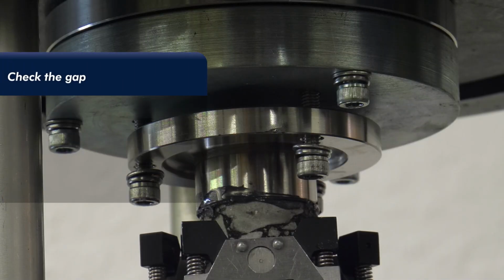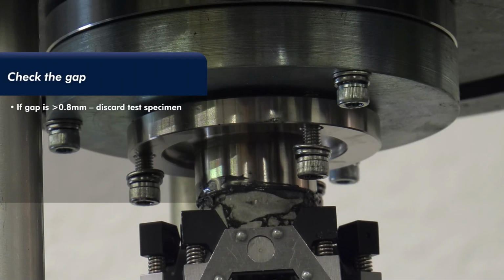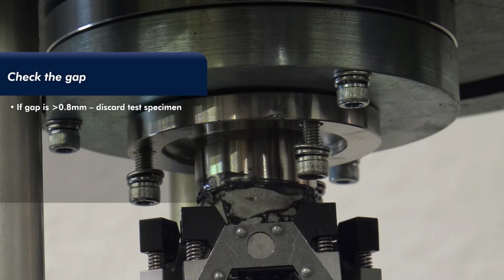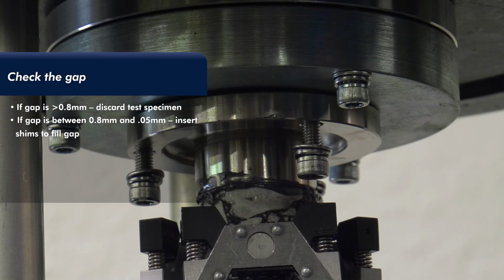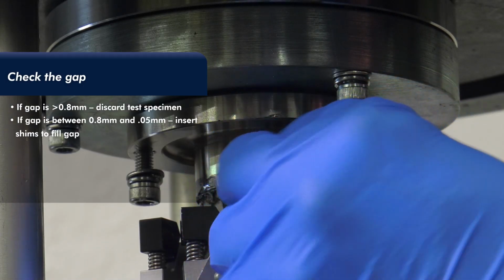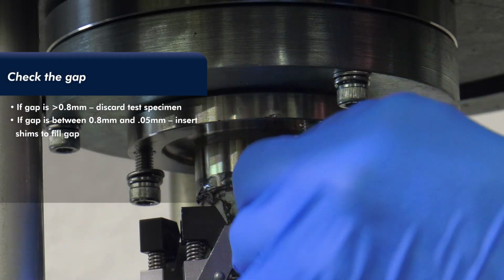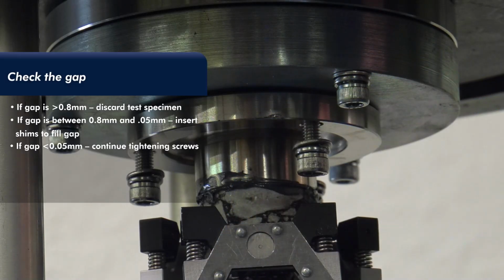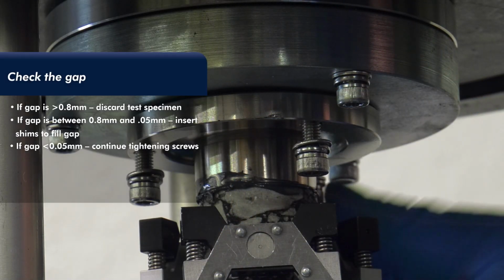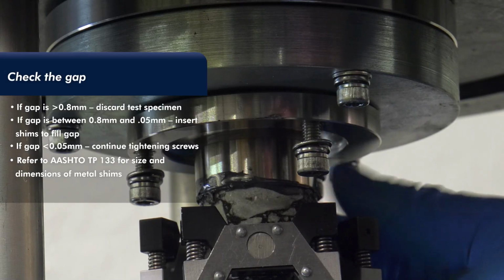Check the gap between the loading platen and the top platen. If the maximum gap is greater than 0.8 millimeters, discard the test specimen. If the gap is between 0.8 millimeters and 0.05 millimeters, insert shims to fill the gap. If the gap is less than 0.05 millimeters, continue tightening screws without inserting shims.